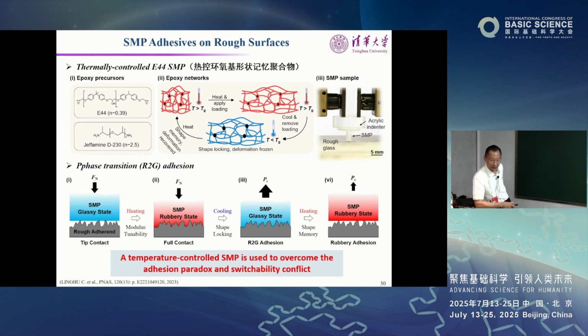Okay, so this one you can use in the following way. Imagine you do a phase transition to adhesion. In a glassy state, this is very high modulus, but cooled down, right? The bluish color means the temperature is relatively low, it's below Tg. In this case, this is pretty tough. This is a rough surface. There's no adhesion. Very small adhesion. Okay, in this state, very small adhesion. You can do the interaction. You pull it up. Very weak forces.